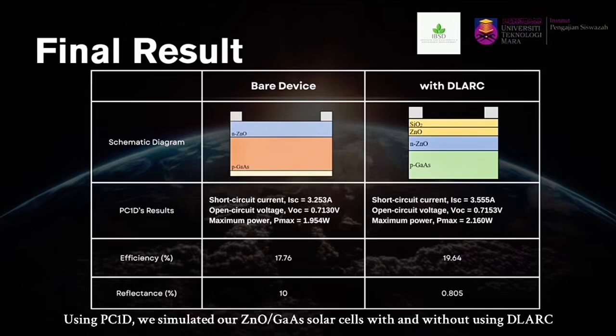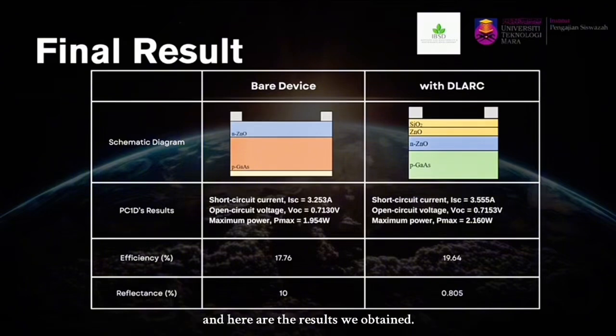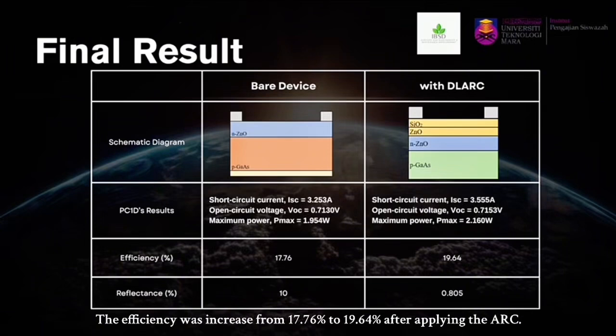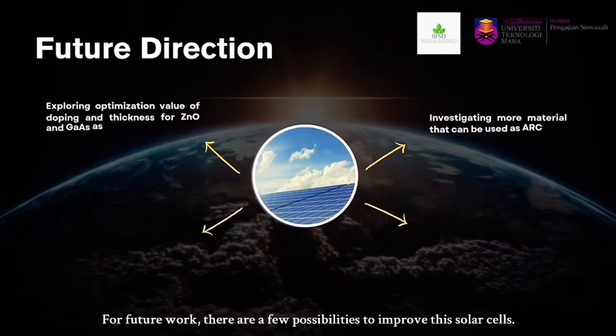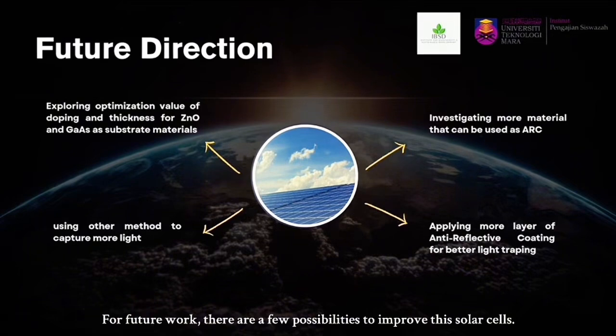Using PC1D, we simulated our zinc oxide gallium arsenide solar cell with and without using double-layer ARC, and here are the results we obtained. The efficiency was increased from 17.76% to 19.64% after applying the ARC. The percentage of reflectance was drastically decreased from 10% to 0.805%.